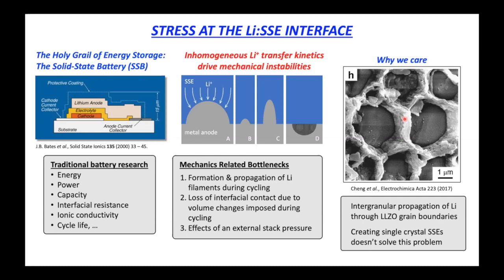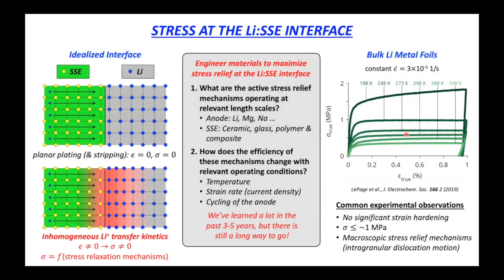And in order to do that, we've got to figure out how to engineer materials and design cells that can prevent the formation and growth of these lithium filaments, right? So to that end, as I said, the ideal goal here is to get this stress-free plating and stripping of the anode. But when we can't achieve that, we're going to have to rely on materials that can intentionally be engineered to alleviate this localized pressure at the interface, right? And in order to do that, we're going to have to know something about the active stress relief mechanisms that are operating in these materials. And we're going to have to know how those mechanisms change in going from one anode material to the next, right? And then, of course, there's the separator side of the puzzle, right?